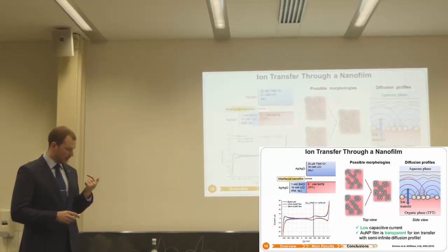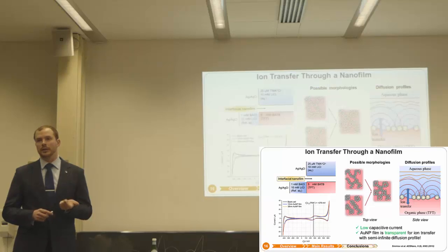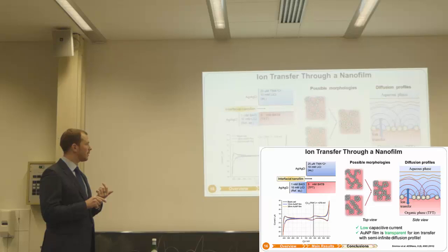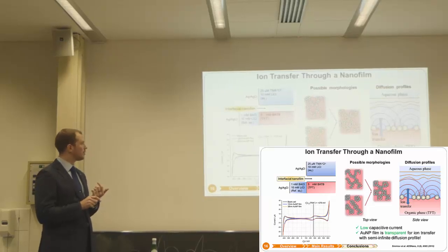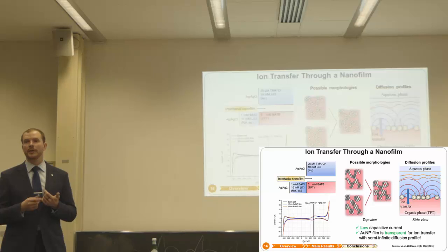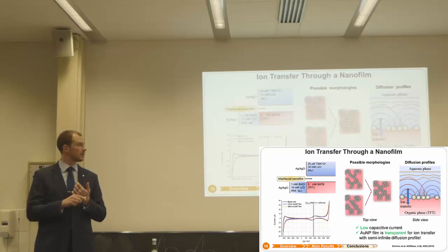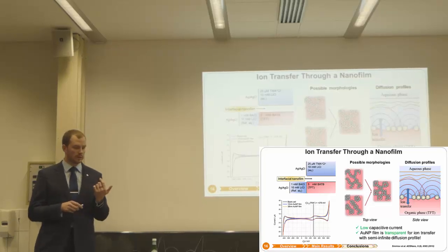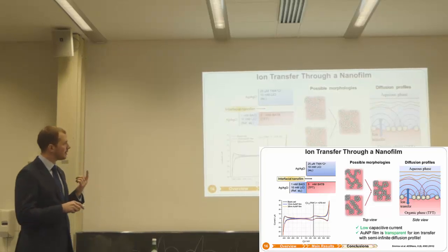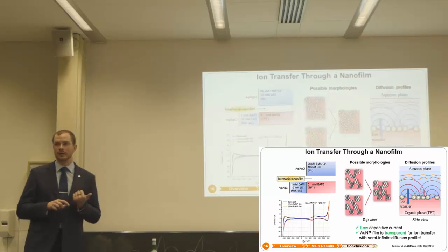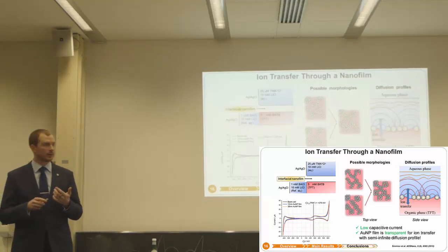Firstly, we studied some standard ions and standard molecules to characterize our film. The idea was that we transfer TMA plus ions from one place to another. And we showed that there is no significant effect from the nanoparticle film on this transfer. So the nanoparticle film is completely transparent for ion transfer and doesn't take part in that process.